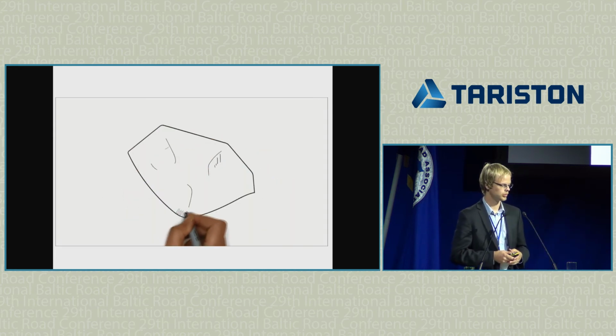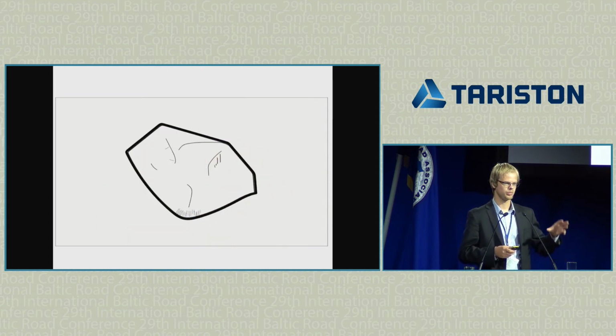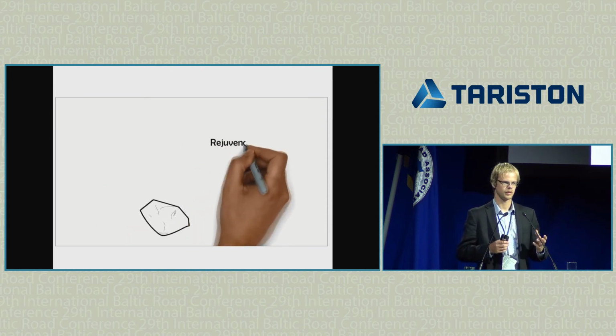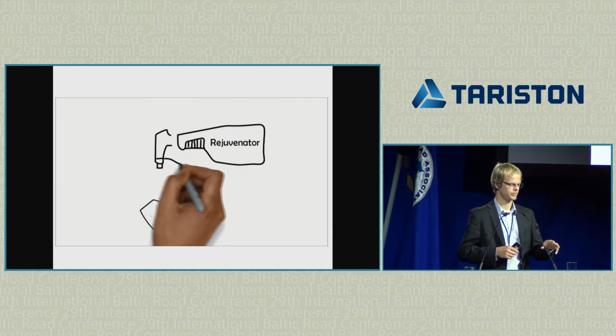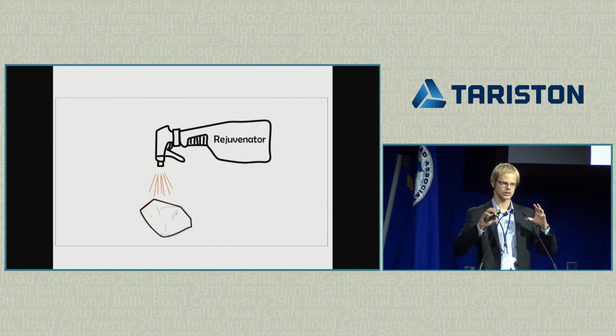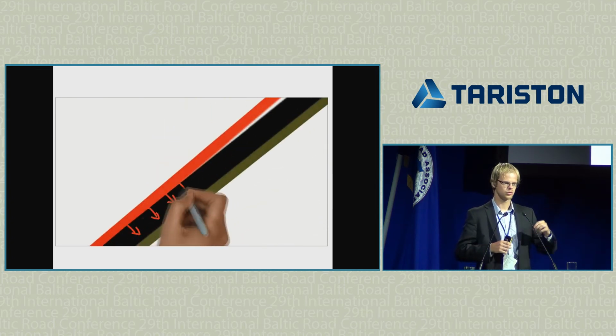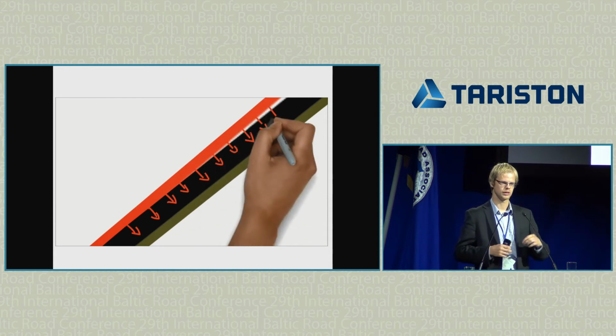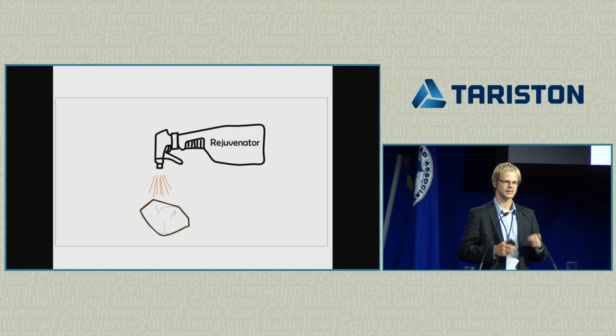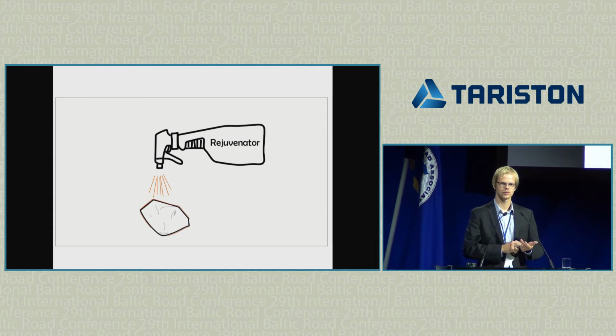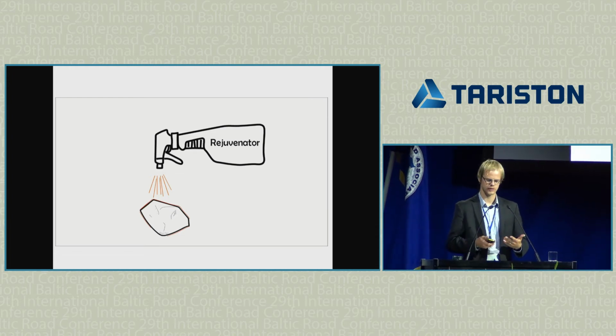Well, now the problem. If we have an aggregate covered with the binder film and we apply a rejuvenator on it, now the rejuvenator is covering the binder film from outside. So in order to blend together, it has to first diffuse into the old binder film. And that's not really so simple, because the diffusion and the mixing process will depend on the aging state of the old binder. It will depend on the rejuvenator. It will depend on the temperature that we're using in the mixing plant. It will depend on the time of the exposure to temperature. So there are all these factors that affect the result.